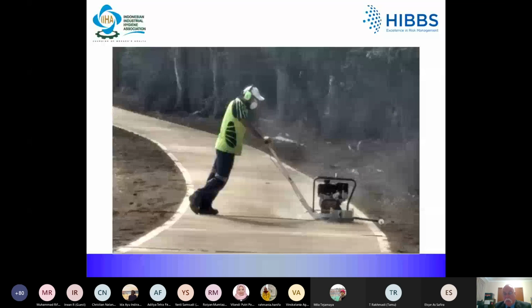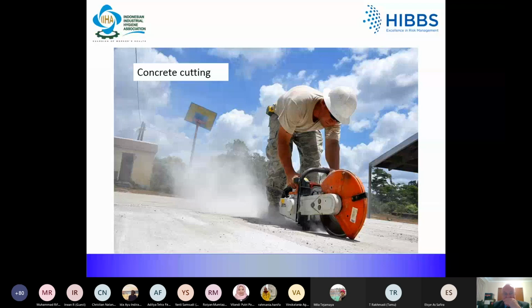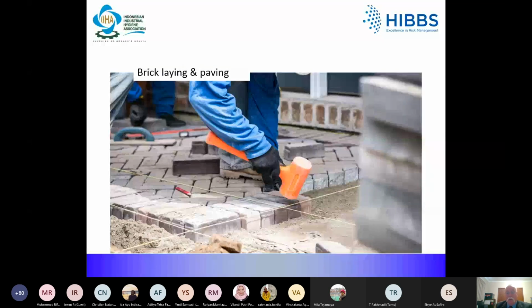There is grinding of concrete surfaces. This bloke's grinding down a section of footpath, where the footpath has moved so that the heights are different. This fella's doing concrete cutting, dry concrete cutting. You'll notice no respirator and also no hearing protection. The laying of brick paving can also release significant levels, or probably not as high as the other operations, but it can release respirable crystalline silica.